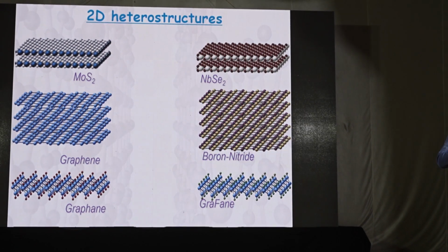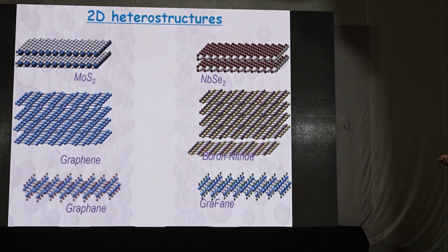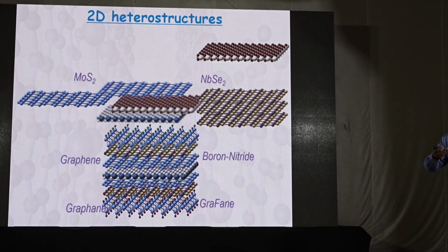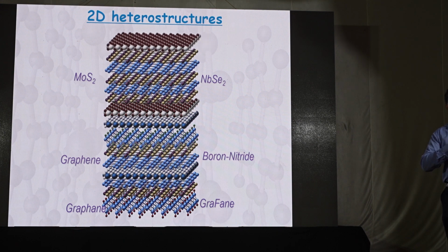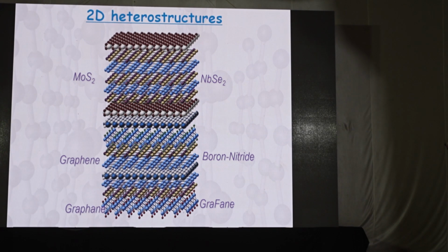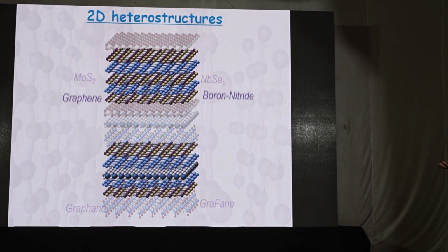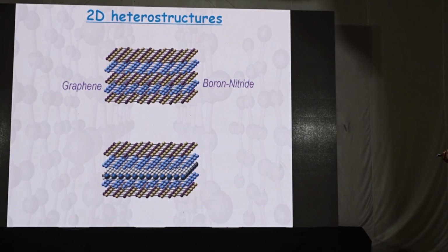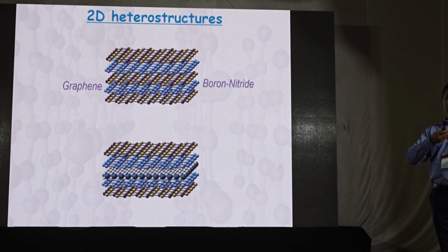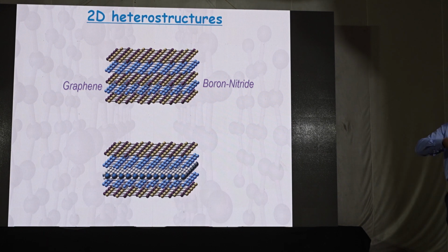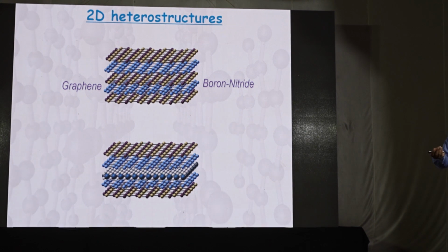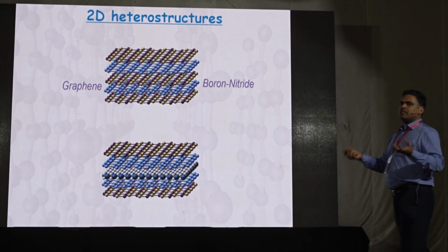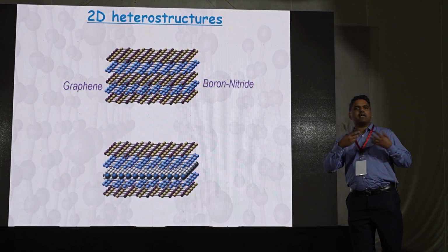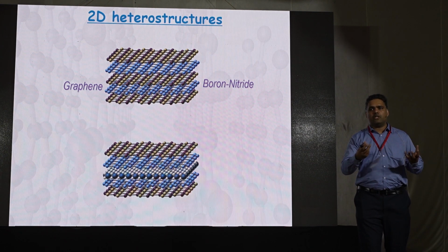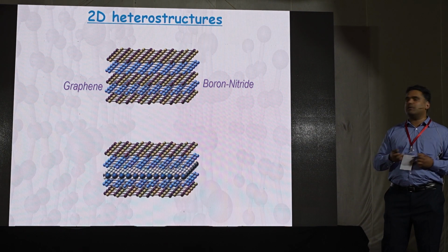From a chemist or material science perspective, we can make new materials by combining all these different materials, by stacking one on top of each other. So this is an example. You take graphene and boron nitride. Graphene is conducting, boron nitride is insulating. You stack one on top of each other, you get basically a conducting, insulating structure. That's a new material. So it's not existing. This material is made in the lab. So that means you can create material with any property you want by designing new materials using 2D materials.